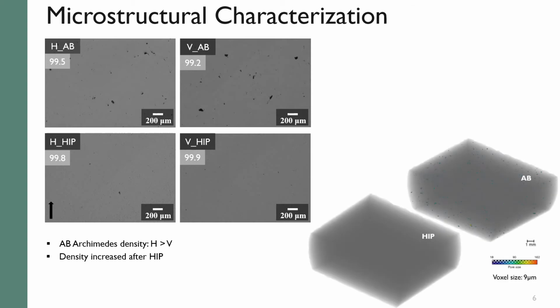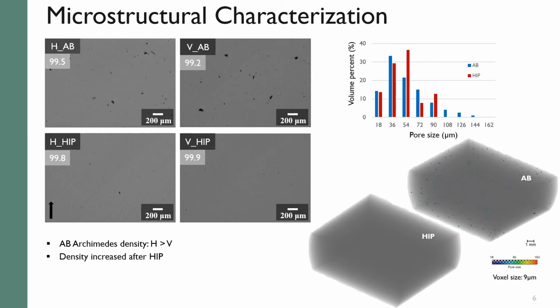As you can also see in the reconstructed micro-CT images on the right side, much lower overall fraction of pores is observed in the case of HIP as compared to as-built. And in this graph, it is shown that in the case of HIP, no pores larger than 90 micrometer were found, so the large internal pores are eliminated after heat treatment.